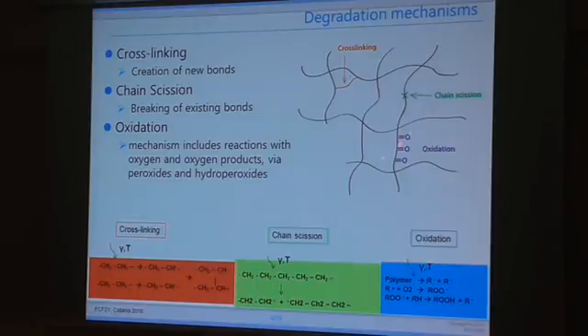So the polymer network microstructure is responsible for elasticity properties. And there are a few mechanisms, like creation of new bonds known as cross-linking, breaking of existing bonds known as chain scission, and reaction with oxygen, the oxidation process, that change and affect this polymer microstructure. They are all happening at the same time during the degradation process, and dose rate affects these three processes. Because of that, it is important to study it.